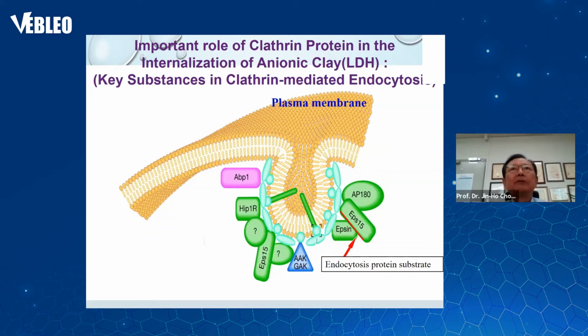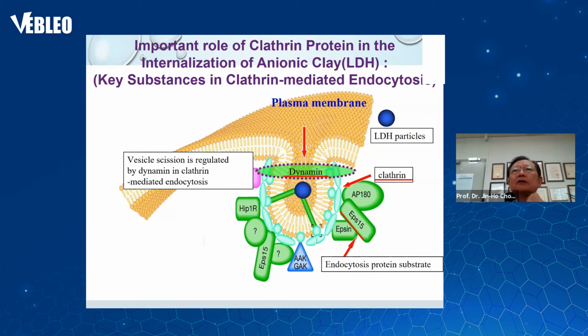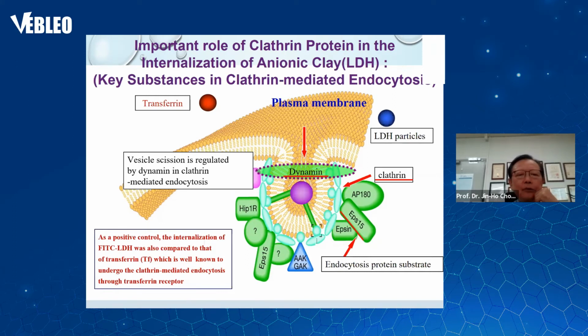And we also confirmed the clathrin-mediated cellular uptake of LDH particles by determining the involvement of certain accessory proteins related to clathrin-mediated endocytosis. Thus, we investigated whether the FITC-LDH is co-localized with the typical endocytic proteins, such as dynamin and EPS15, and others. Dynamin regulates the endocytic vesicle formation in different endocytic pathways, and EPS15 is involved in regulating clathrin-coated pit assembly. As a positive control, the internalization of FITC-conjugated LDH was also compared to that of transferrin, because transferrin is very well known to undergo clathrin-mediated endocytosis through the transferrin receptor.